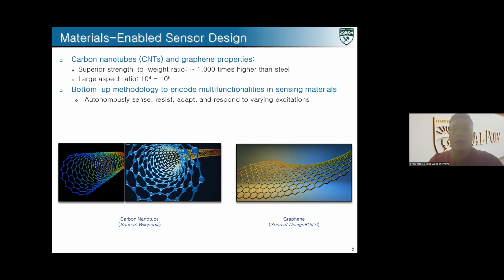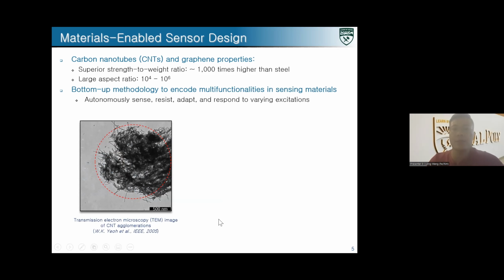And I use additive manufacturing approaches to incorporate these nanomaterials into a scalable functional material system. When it comes to the scalability and manufacturing aspects of these nanomaterials, one of the major challenges is that these materials tend to agglomerate, basically forming inhomogeneous features in a larger material setting. And these inhomogeneous features, or agglomeration, will compromise the overall material property and performance.